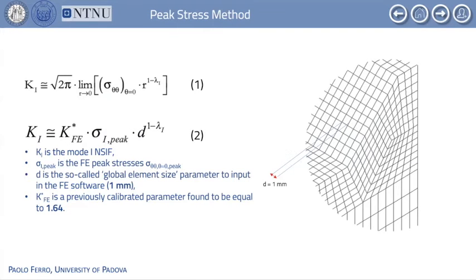When considering residual stresses, the notch stress intensity factor is called the residual notch stress intensity factor, and a rapid technique used to calculate it, even by means of 3D numerical models, is the peak stress method. It allows estimation of the notch stress intensity factor and the residual notch stress intensity factor starting from the opening peak stress calculated at the V-notch tip with a coarse mesh, according to equation 2 in this slide, where D is the average element size adopted to mesh the weld toe, and in this work D is equal to 1 millimeter.